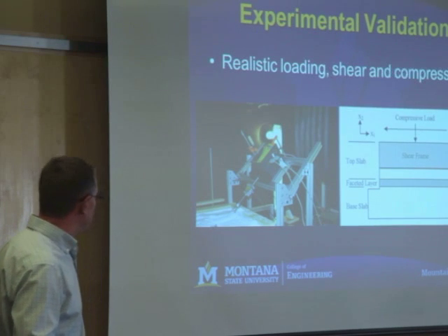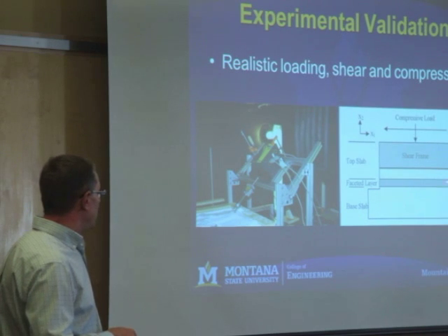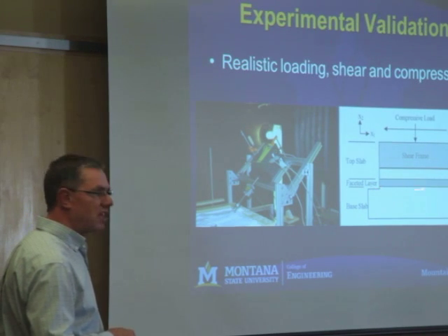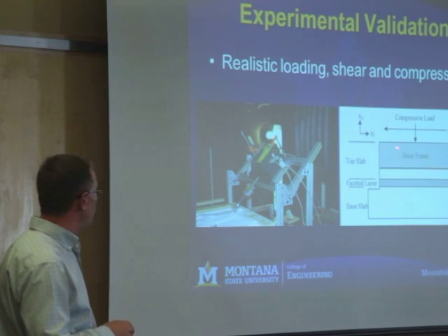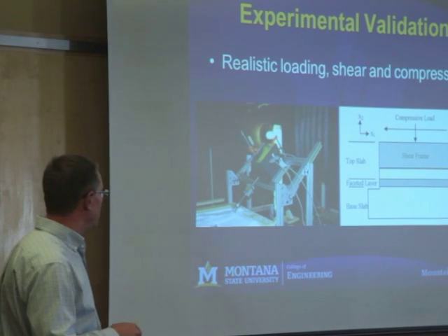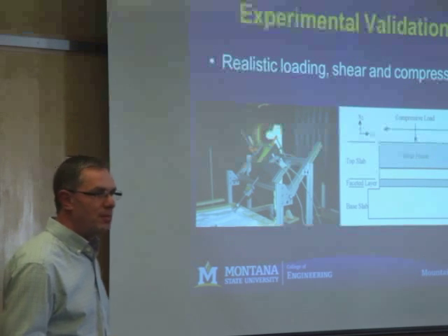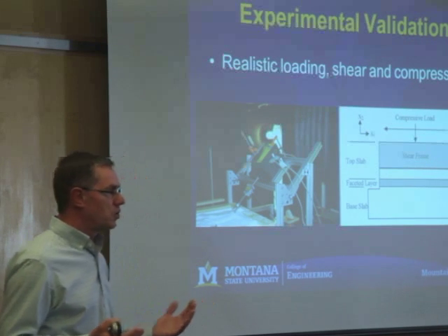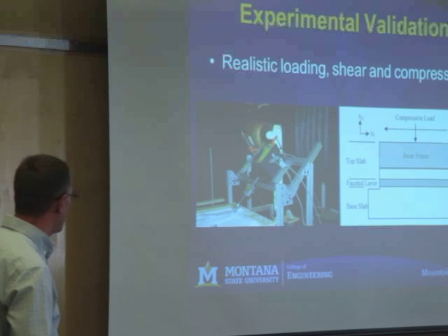This is one of our standard setups that we're using right now, where we have a base layer. We grow some sort of a faceted layer on the surface. We subsequently bury it with a shear frame on top. We re-excavate the shear frame like you see here, and then we're able to put this testing apparatus on here where we can simulate a combination of normal and shear load, so you can get slope angle and load very precisely on that, whatever condition that you want.